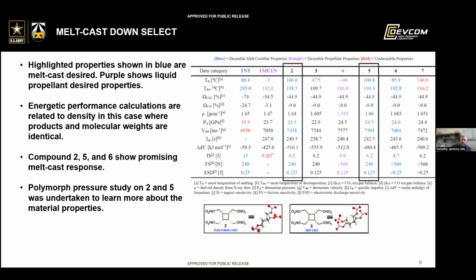So looking at TNT, you can go down and see there's a melt temperature at 80 degrees, and the decomposition is about 300 degrees. And then working down, you get to a detonation pressure of 19.3 and a detonation velocity of 6950. So these are not really favorable numbers. You'd want to have something higher than that. In fact, some of the materials produced in this study have higher numbers than that.